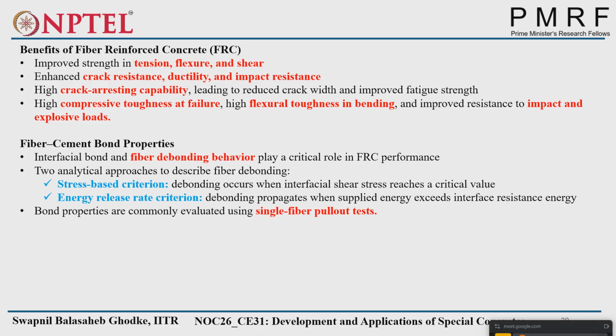so fiber cement bond properties. We saw interfacial bond characteristics and fiber debonding behavior play a critical role based on the embedment critical length. Whatever the amount of length available in the concrete matrix, based on that, interfacial bond and debonding will be observed.